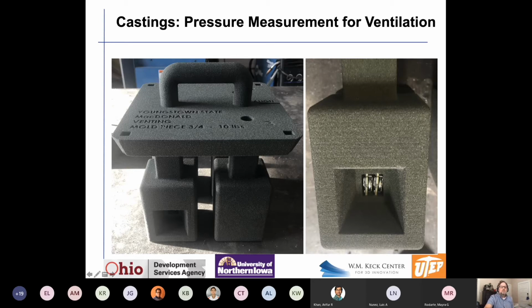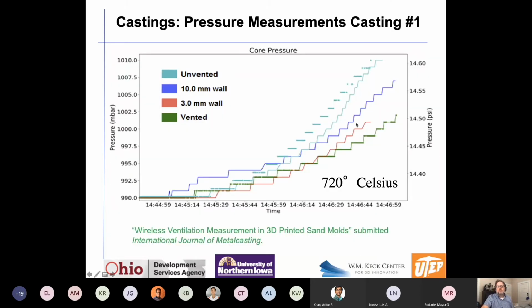And then in this one, there's no ventilation, but this hole right here is like a chimney that goes all the way down, and it lets the gases escape more easily. And that's an advantage of 3D printing. And so we did that, and sure enough, we see that the unvented case goes up higher. The really vented case still has pressure, which was a little surprising, but not as much. And then there's 2 intermediate cases as well.